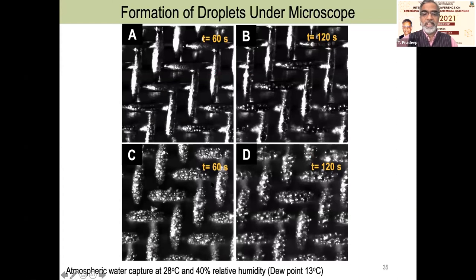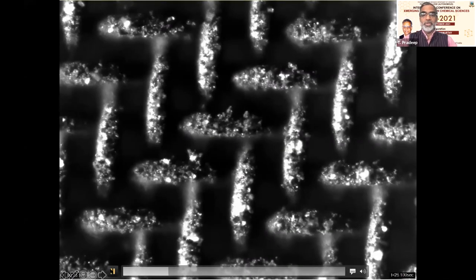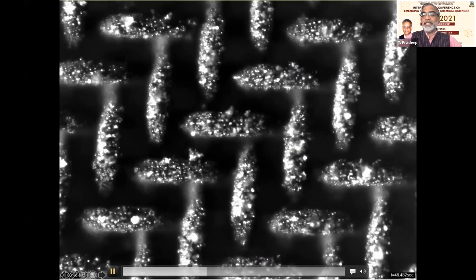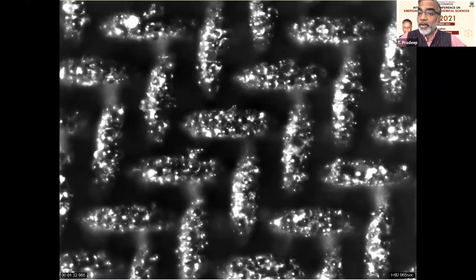So here is a surface. This is an optical micrograph. You can't see the wires here because it is optical microscopy. But in the course of time, from 60 seconds, 120 seconds, et cetera, with a normal surface, you don't collect a lot of water. But on these kinds of surfaces, wherein there are nanowires, you collect a much larger quantity of water.